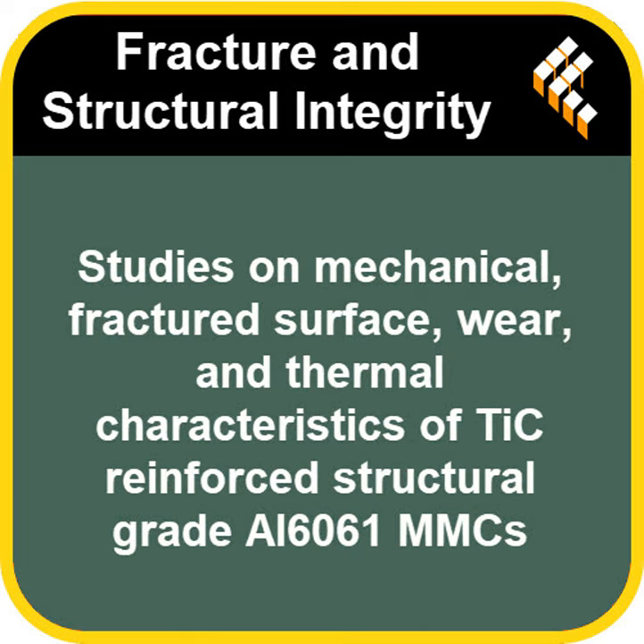You guessed it. The research found that increasing the weight percentage of reinforcements beyond 9% actually led to higher wear loss. That persistent issue of particle agglomeration seems to be the main culprit again. Those clumps strike again. Yeah, they create uneven load distribution, stress concentrations, and can even get pulled out, making the material more prone to wear. It just unequivocally underscores the importance of finding that optimal balance.